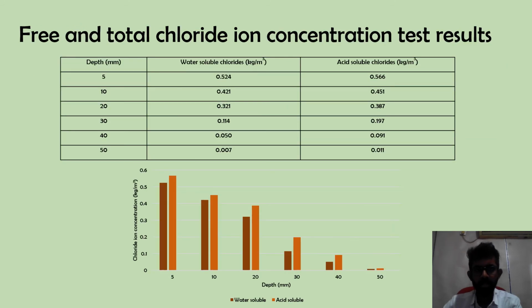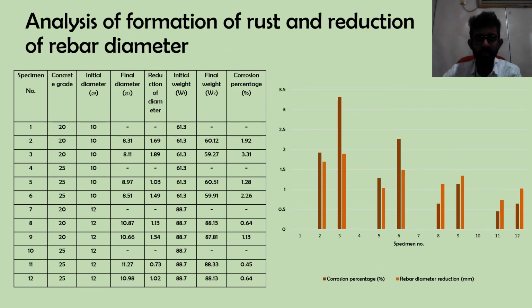Free and total chloride ion concentration test results. It can be seen that the acid-soluble chloride ion concentrations are higher than that of water-soluble chloride ion concentrations throughout all depth levels. Analysis of formation of rust and reduction of rebar diameter. It can be seen for both grades that the corrosion percentage has increased, and it has decreased with the increase of rebar diameter as well.